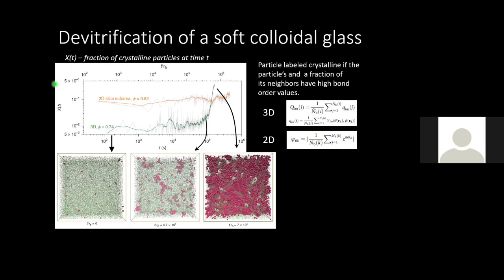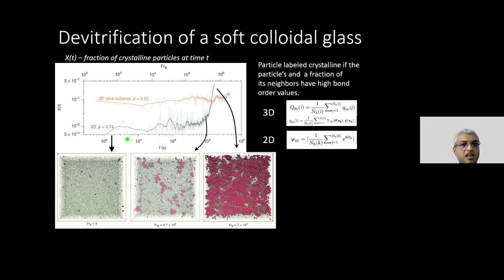Okay, thanks. Yeah. So, like I said, this sample is completely frozen on the particle scale, but has essentially crystallized. Now I can plot for you the crystallinity, which is just the fraction of crystalline particles in my imaged volume as a function of time. Let's focus on the sample from a 3D experiment at 0.74. You will see that there is a long period in which nothing happens. And suddenly crystallization seems to set in, and you see this sudden jump in crystallinity.